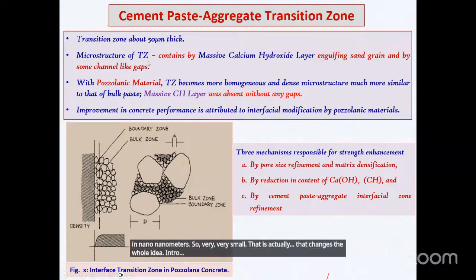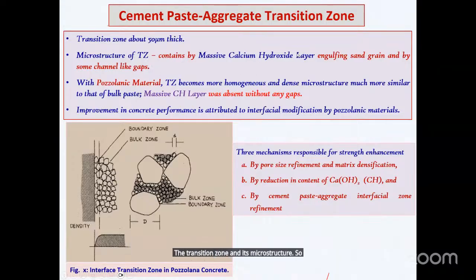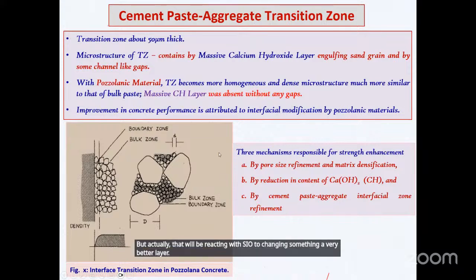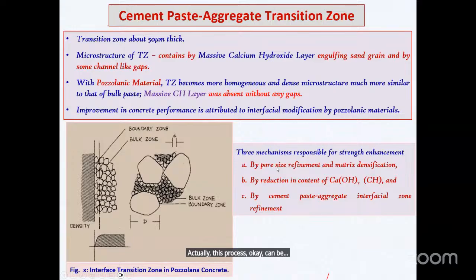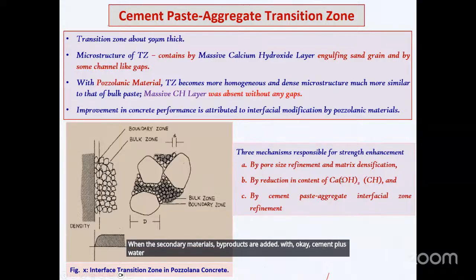And there is a transition zone, the transition zone and its microstructure. So having a calcium hydroxide layer, but that will be reacting with SiO2, changing it into a much better layer. This process can be described: there is a pore size refinement and matrix densification. When the secondary materials, byproducts, are added with cement plus water, or in general calcium hydroxide, calcium hydroxide reacts with the SiO2 present in the byproducts. So there is a pore size refinement and a densification of the matrix in and around the aggregate.